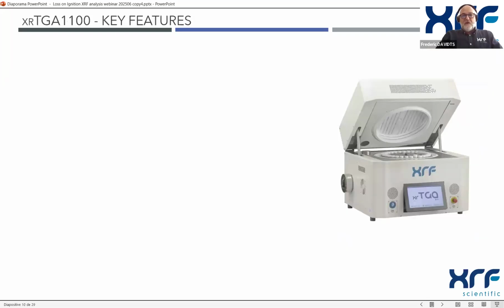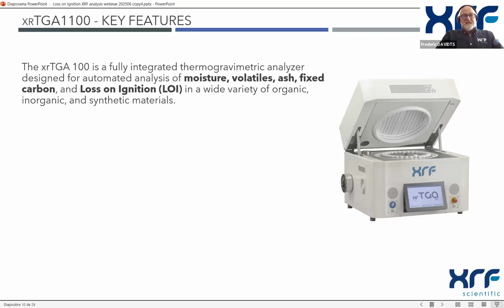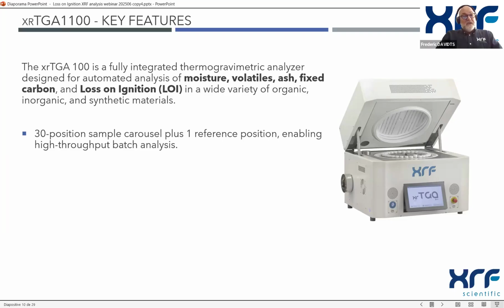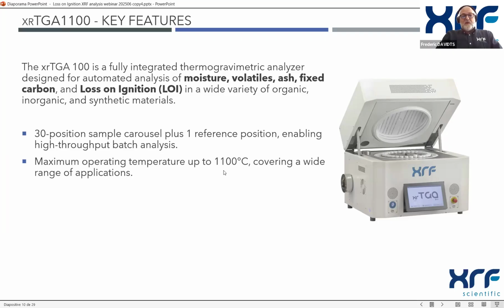So the key features of our TGA, the XR TGA 1100. Again, it's for analyzing moisture, volatiles, ash, fixed carbon, loss on ignition in a variety of organic, inorganic, and synthetic materials. We have 30 positions for the samples plus one reference, so it's made for high throughput. We can reach 1100 degrees, and it's an advantage because we can reach some norms which require higher temperature, but also it's interesting because we reach the fusion temperature, and in some industries, they prefer to do the loss at the fusion temperature